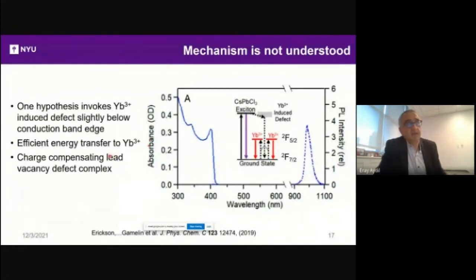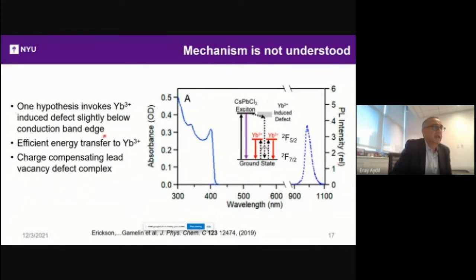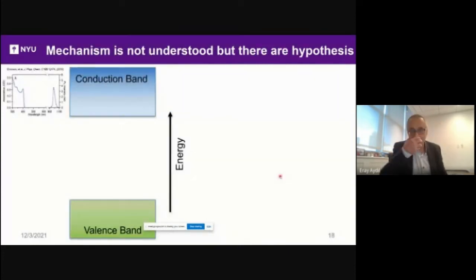Now, you might ask, why does this happen? And the answer is we don't know. The mechanism is not understood. It is a lucky accident. But one hypothesis invokes a ytterbium 3+ induced defect slightly below the conduction band edge, and you have an efficient energy transfer to ytterbium 3+, and a charge-compensating lead vacancy defect complex that mediates that transfer to the ytterbium.